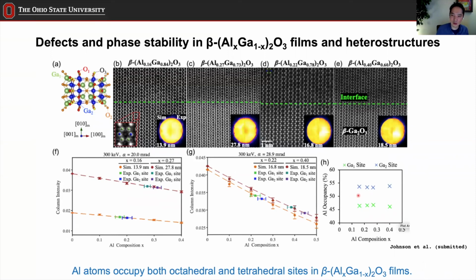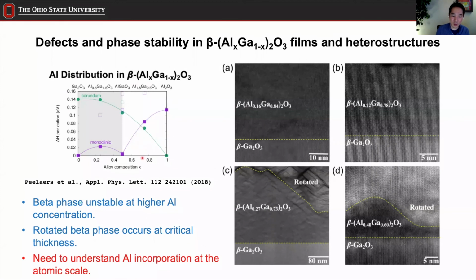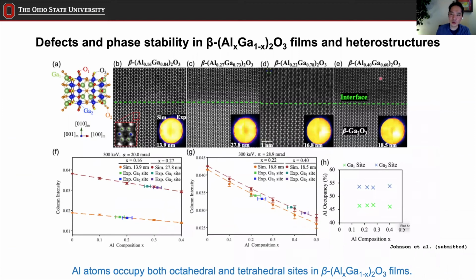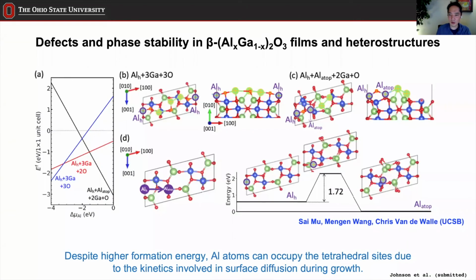So therefore, it doesn't always occupy this site only, and that's where we see this deviation between the number here, which is 70%, and the 40% here. And it's likely that that is what's limiting the growth of the structure at high aluminum composition. So with that, our collaborator Chris Van de Walle and their postdocs have come up with a new simulation of what might be happening in the growth. They assume that this is unlike the bulk state that they simulated before. Their hypothesis was that maybe during the growth procedure, the surface diffusion kinetics may dominate, and then that may end up giving lots of aluminums in tetrahedral sites. And that's what they simulated here.